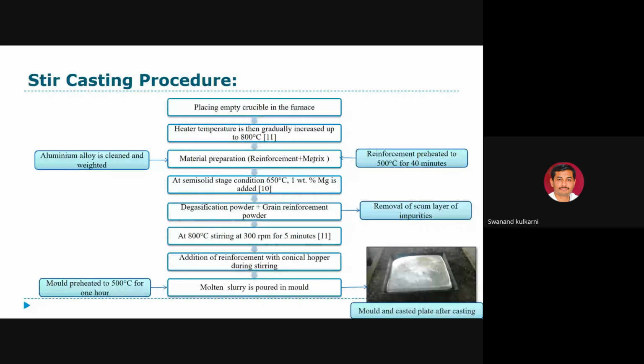Grain refinement tablets are used because they involve a chemical reaction with the grains, and grain formation happens. The smaller the grain size, the better the properties. So in this liquid process, particularly the stir casting process, grain refinements are generally preferred in order to have better mechanical properties. And then the scum is removed. After removing the scum, stirring is done at a specific RPM, which we have decided from previous research or from our experience. Stirring for a particular time is carried out, maybe from 5 to 10 minutes; many times 10 minutes is used, or if sufficient, 5 minutes is also used.